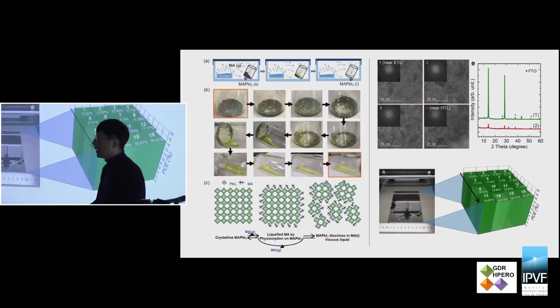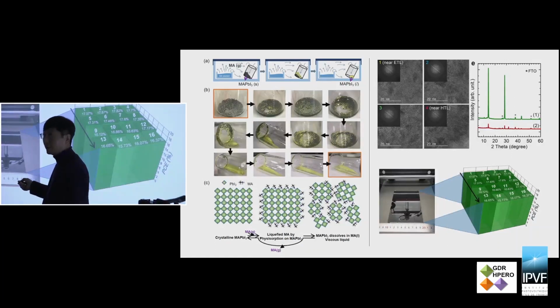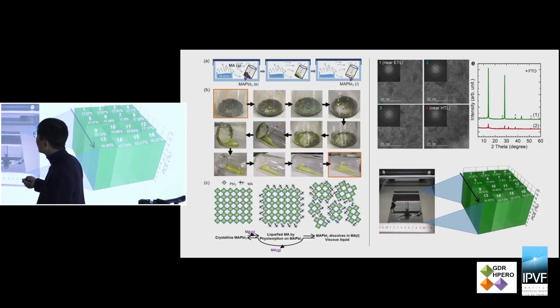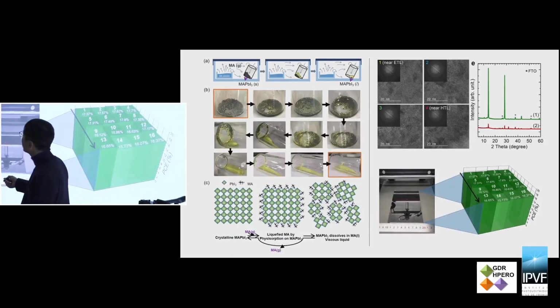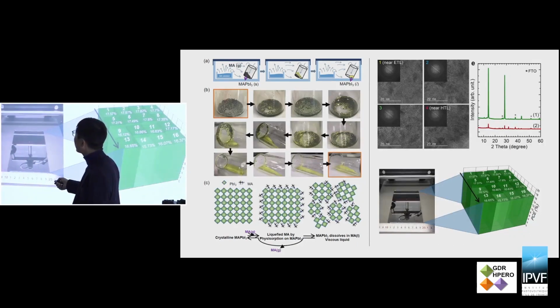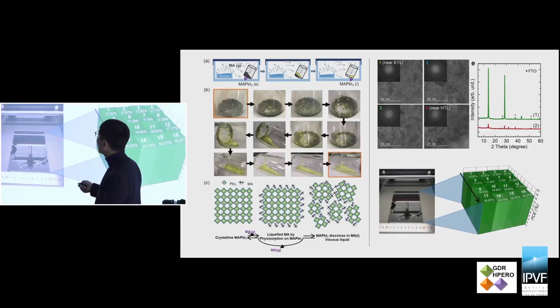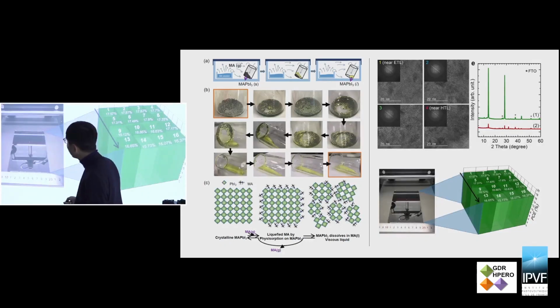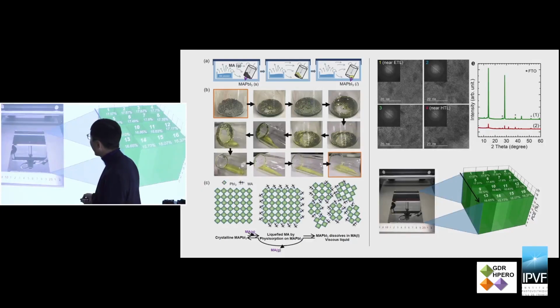And here is the detail. For instance, methylammonium lead iodide powder. First, you have to prepare a methylammonium lead iodide solid sample, and then in a closed system, you produce methylamine gas from methylamine solution. The methylamine gas can dissolve this MAPbI3 powder, and eventually you have a liquid. So this is a very amazing process. We do not use any liquid to make the solution, we just use the gas phase. The gas to liquid phase transition is due to the gas molecule being adsorbed on the surface of the perovskite powder, and the adsorbed methylamine gas has a much stronger interaction as compared to free gas molecules.